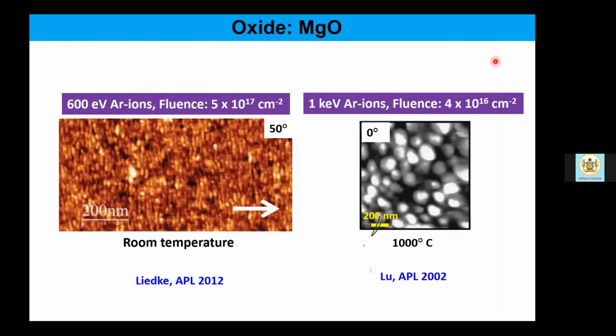Then comes the example of magnesium oxide. So this is another example where ripple formation is possible. Nothing new, but at 0 degree incident angle, dot formation was taking place at 1000 degrees centigrade. Whereas at 50 degree incident angles, these authors reported on ripple formation. Okay, perpendicular mode ripple formation. That means ripple orientation was perpendicular to the projection of the incident ion beam.